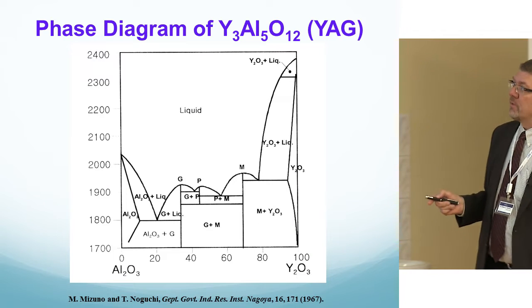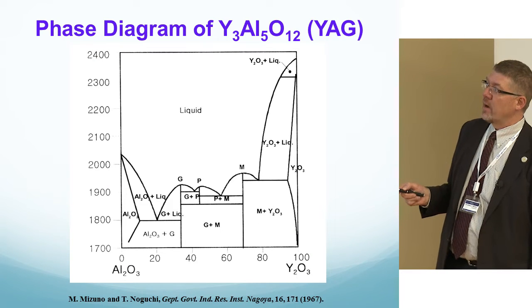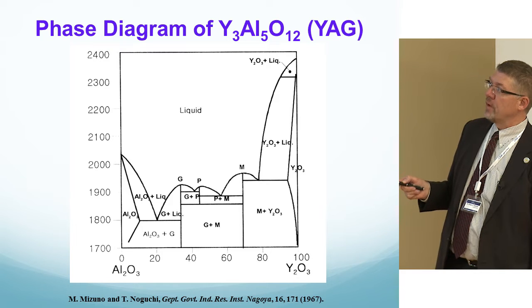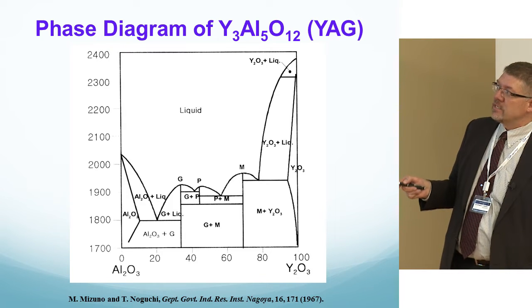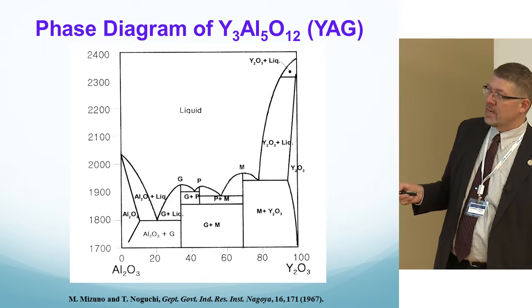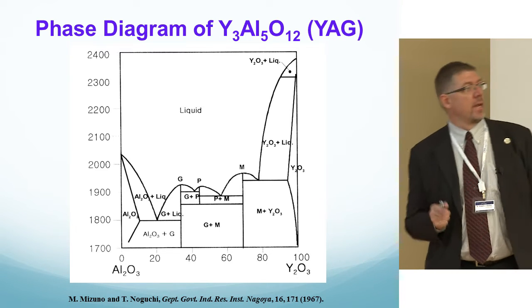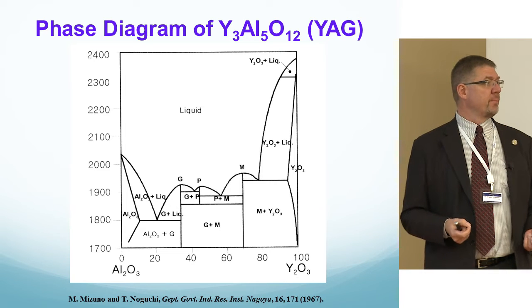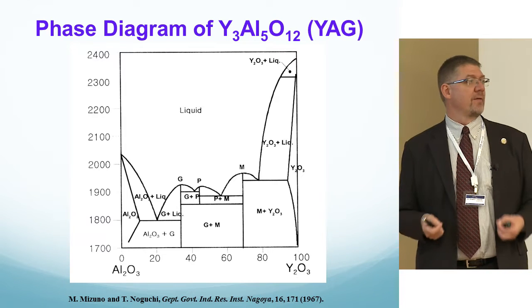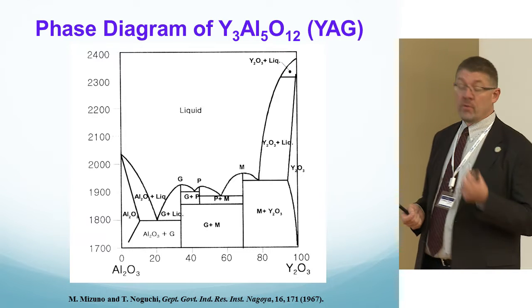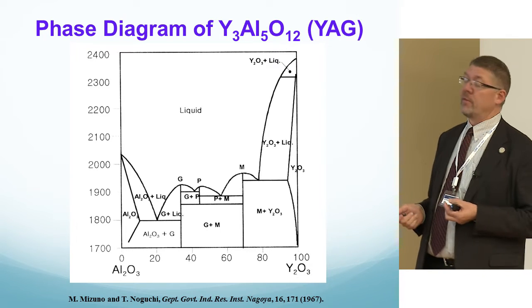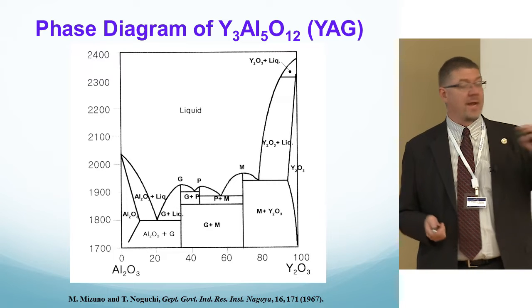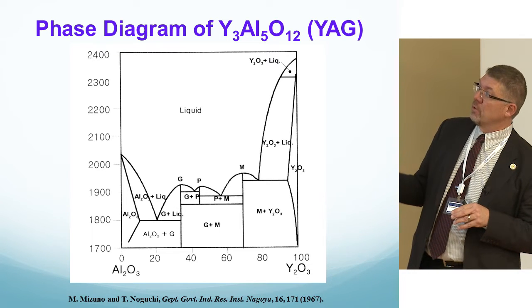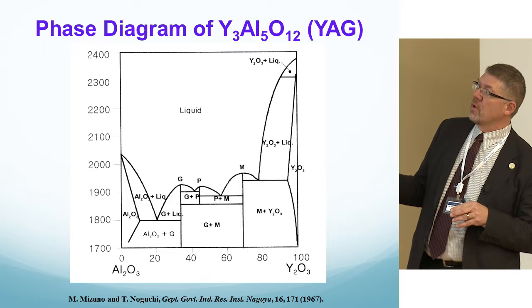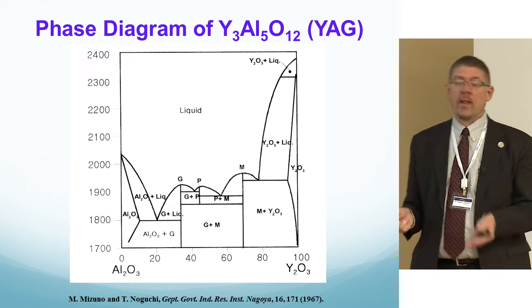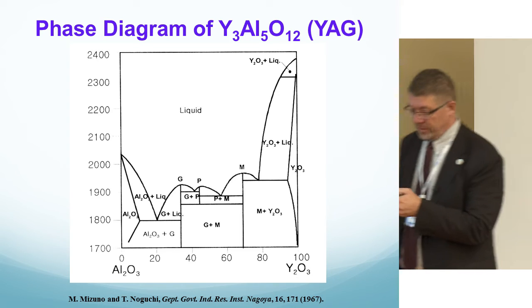So as I mentioned, with YAG, you've got three different phases. You've got the garnet phase, which sits right here, the perovskite phase, and the M phase. So you have got to be exactly on stoichiometry here between the aluminum oxide and the yttrium oxide to hold it at a garnet phase. That's controlled by temperature. So when you're making your powders, you have to have just strong temperature stability. If you're growing the crystal, holding it away from those other phases is much, much more difficult because you can't have any temperature fluctuations, because if you look over here, any kind of up or down on the garnet phase, and you're going to drive it to a different phase. With the powders, it's all done in the powder processing.